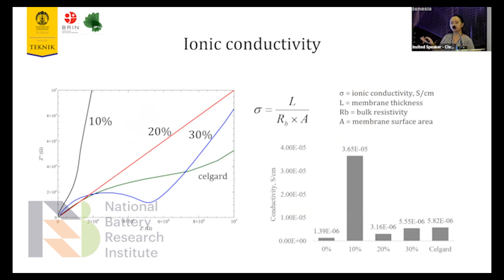So the left side is the Nyquist plot where we plot our impedance obtained from the potentiostat measurement. And we can see that this is the variation of salt concentration. So we have 10% salt, 20% salt, 30% salt, and at the most right side, we use a Celgard separator, which resembles commercial battery. We can see that 10% salt concentration gives the best ionic conductivity, even better than the commercial battery that used commercial separator.